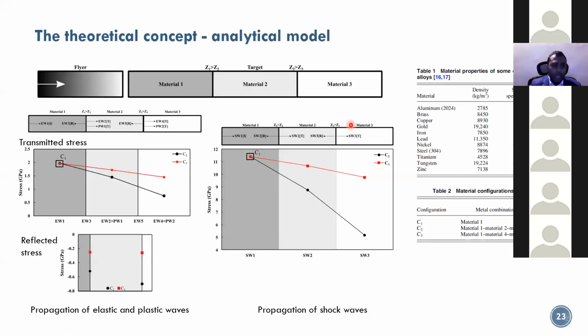So in an impedance graded system, as you can see, I won't explain all these details on the slide, but what you would get is a reduction in stresses, as you could see in both the red and the black lines. There's a reduction in stresses as you go through the material. Now the black line is for a material system with a high impedance reduction from material 1 to material 2 to material 3. There's a high impedance reduction. But in the red one, the impedance reduction is gradual.